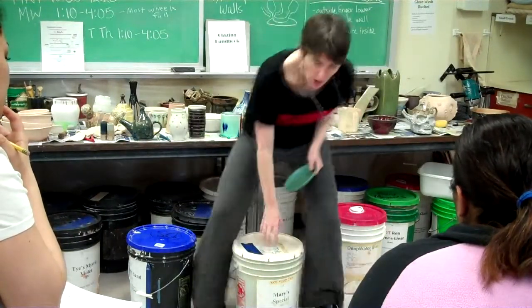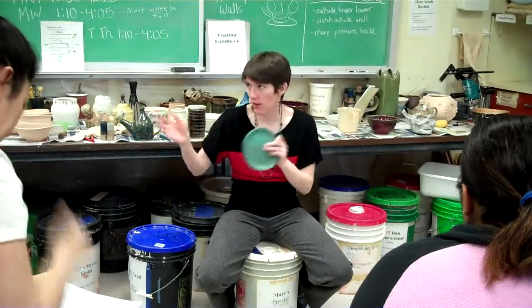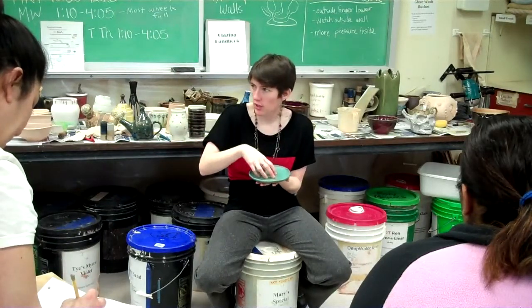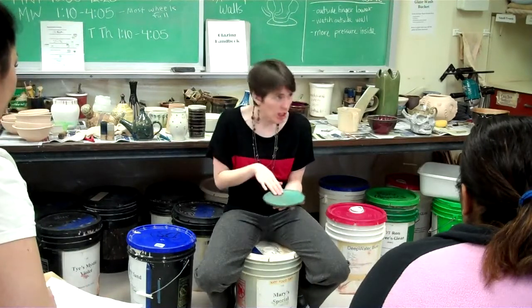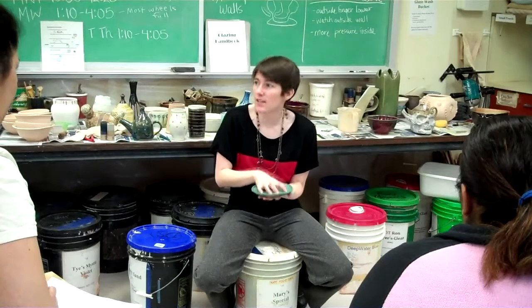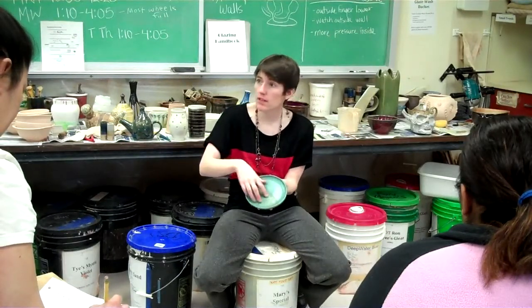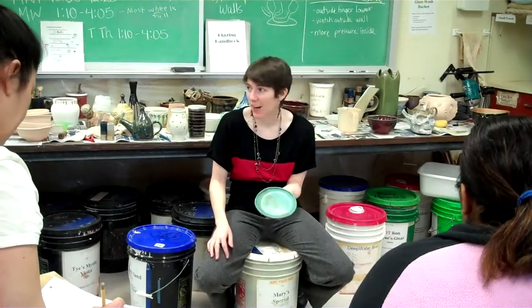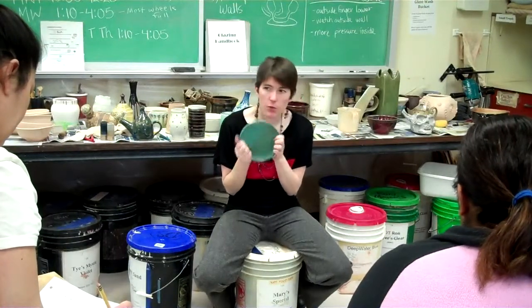A couple years ago we did a set of tests where everybody glazed bowls, and the advanced students glazed bowls, and then we set either a lemon or some detergent in it, left them for a few days, and we then observed any changes. If the glaze changes a little bit, that shows us that it's not a stable glaze, it leaches a little bit, and potentially some of the chrome that's in this glaze comes off into your coffee or your SpaghettiOs or whatever you're eating or drinking out of it. So we determined that we couldn't say that this one was food safe.